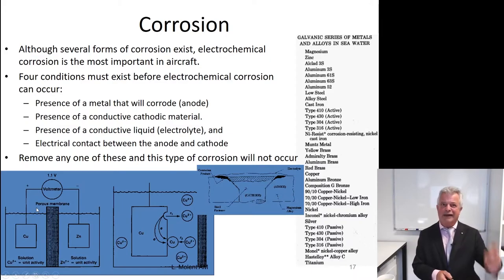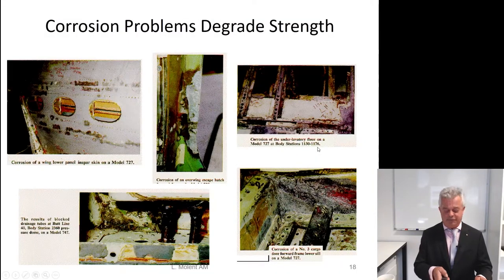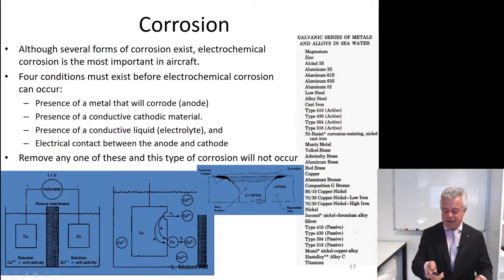Environment, salt water, great electrolyte, which gives you the conductivity. Okay, and what happens is that the active material gives off electrons, it loses material, and that is basically what corrosion is. And sometimes the corrosion will pile up and it would be problematic, but we'll talk about why corrosion is a problem in a moment. But you can really set up your airplane to be problematic by, say, choosing the wrong materials, for instance, and putting them in close contact.